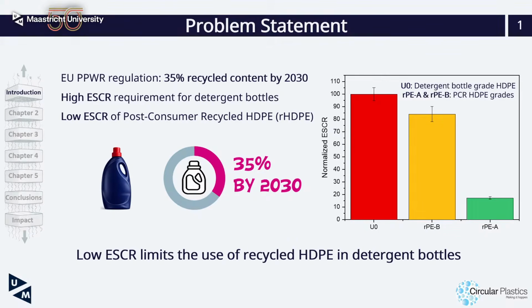When exposed to surfactants, such as detergents, HDPE becomes more susceptible to cracking, even under low levels of mechanical stress in daily use or storage. This means that this material must have a sufficient level of ESCR to maintain packaging integrity. So the challenge is that post-consumer recycled HDPE often shows lower ESCR than virgin HDPE in detergent bottles. As a result, the low resistance of recycled HDPE to stress cracking limits its use in producing new detergent bottles.